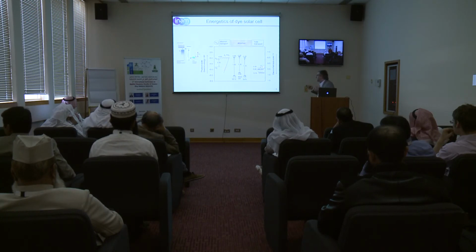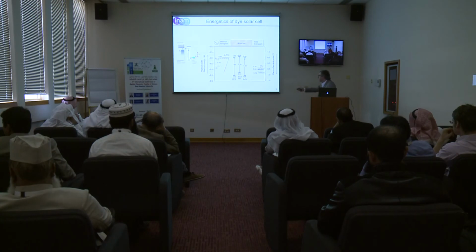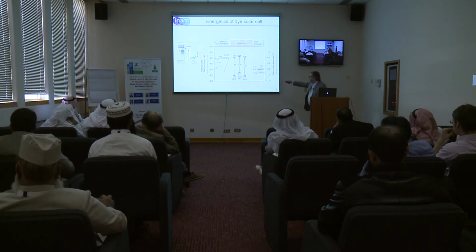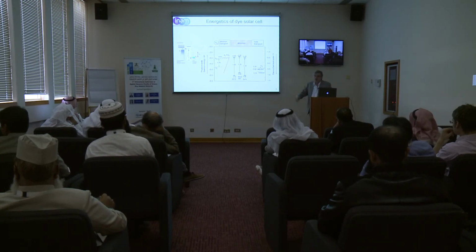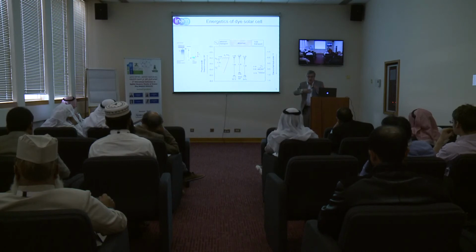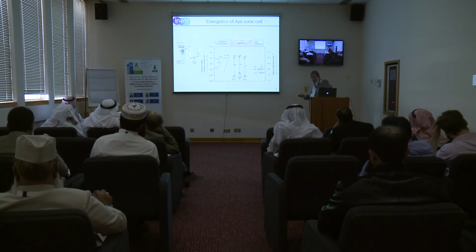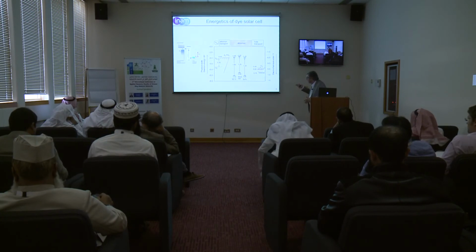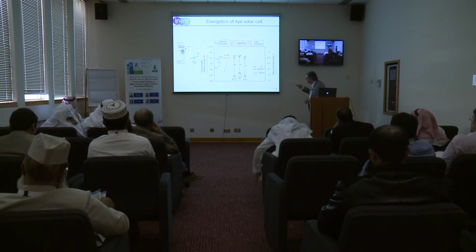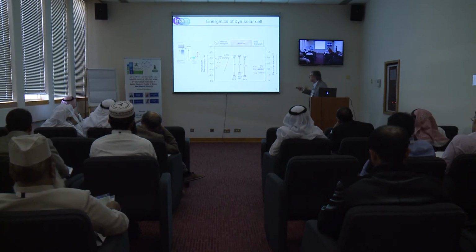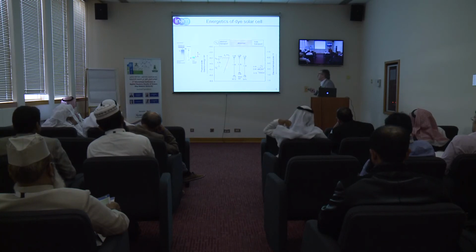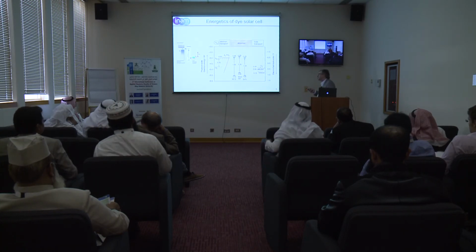This is the iodide redox couple, okay, and this is the ground state of the dye. You see, this is a very big difference, which is the main problem of the dye-sensitized solar cell. You lose here 0.7 to 1 volt. You lose it for dye regeneration. So then redox carriers with cobalt were developed, like here, and then it's a much higher voltage. So with respect to this reference, we can plot now the density of states, and we can know also the energy level of the dyes. So we can do a very good characterization in order to optimize the dye solar cells.